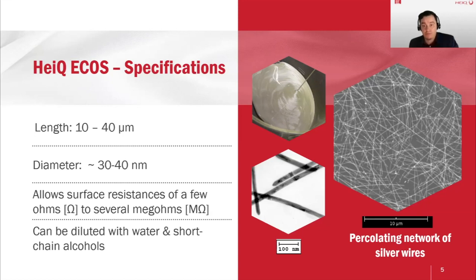And this coating formulation can be applied to a variety of substrates. For example, to polymer films, to glass, to transparent plastics, to textiles, and many other substrates. And on the right-hand side here, you can see a SEM image of a coated polymer film.